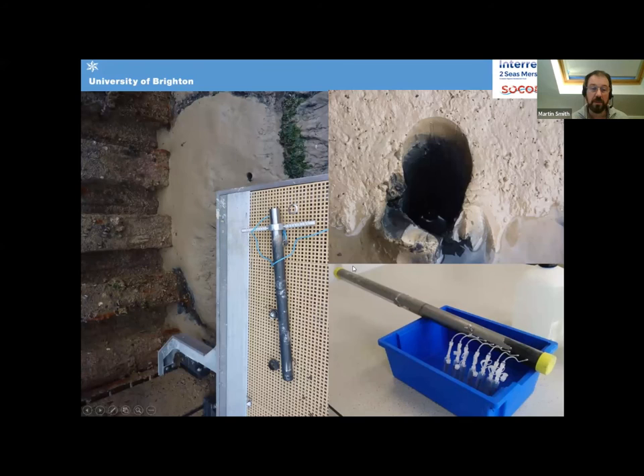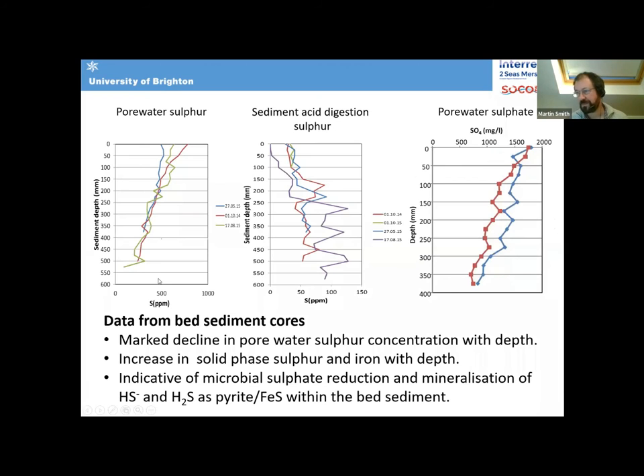We then move to sediment sampling, usually a straightforward core with a plastic core tube inserted into the bed sediment. We take pore water samples. So this is using a Rhizon technique. It's a microporous bar, basically just connected up to syringes. And we take the pore water sample directly out of the tube, so with no exposure to atmosphere prior to analysis.